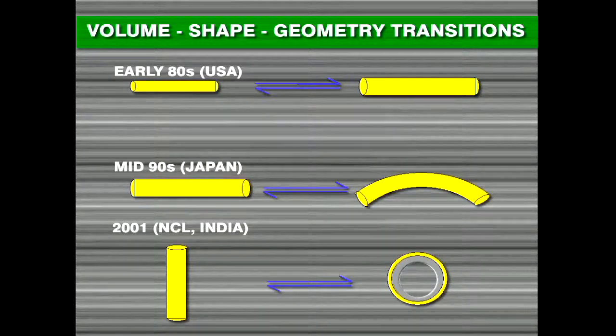Now the interesting part is that if you see, the early breakthroughs came in the US. Professor Tanaka from MIT was the master who actually showed these volume phase transitions. So you can take a small sphere, put it in water, it will become a big sphere, and reversibly can collapse and go back. So if you have a small cylinder, it will become a big cylinder and collapse and get into a small cylinder. That was the work. The Japanese in the mid-90s actually did the bending part of it, basically, by using a variety of means, including the biomimetic. And the breakthrough that we had in NCL was that a cylinder could be converted not only to a sphere, but to a coconut-like structure. And that could be done reversibly, by the way. In fact, Nature called it the Indian rope trick, by the way, when this paper was actually published.